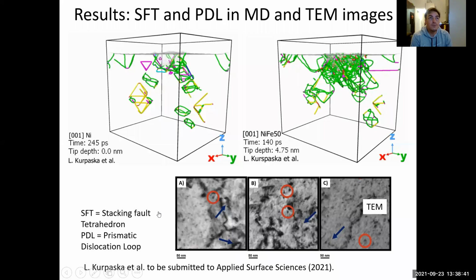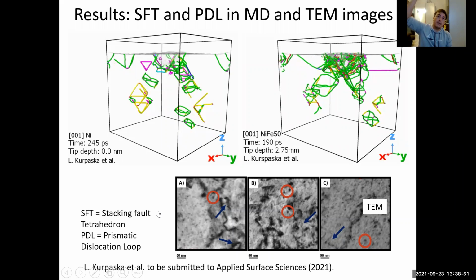I already reached 5 nanometers of the indentation for loading. There it goes, the dislocation, the unloading process. So the tip is going up, and you have more time, and you see the difference. The mobility of the prismatic dislocation loops is really slow. There is one stacking fault tetrahedron formed, really small there, and the simulation is done.